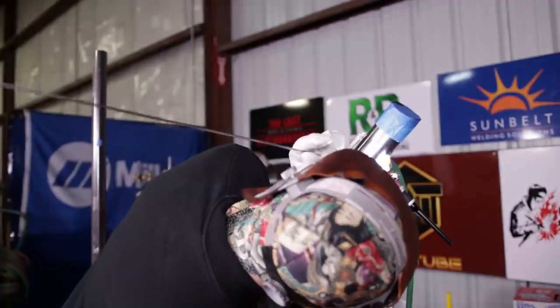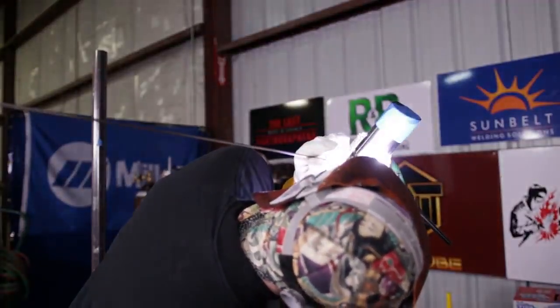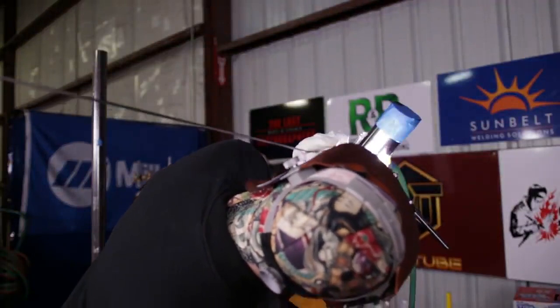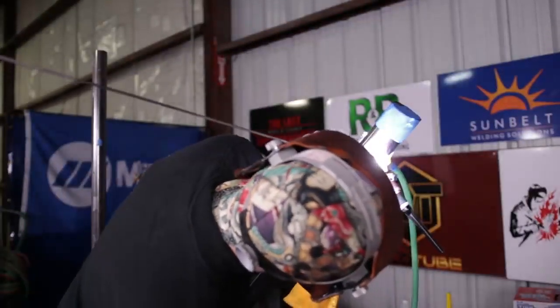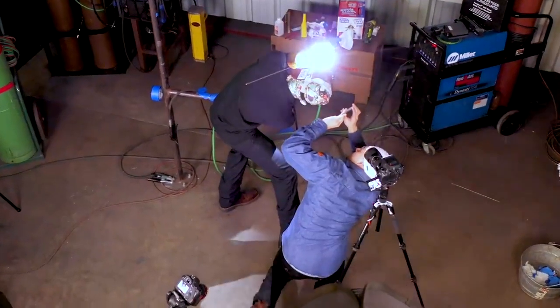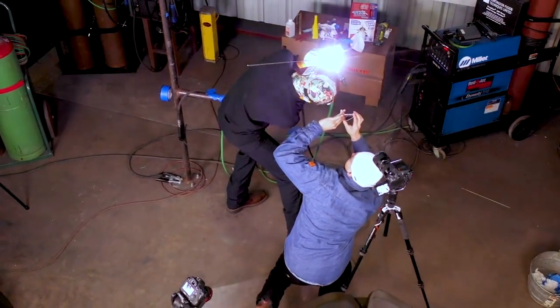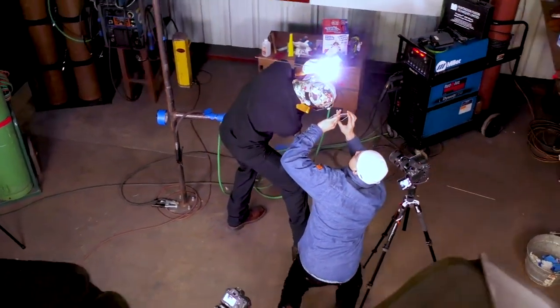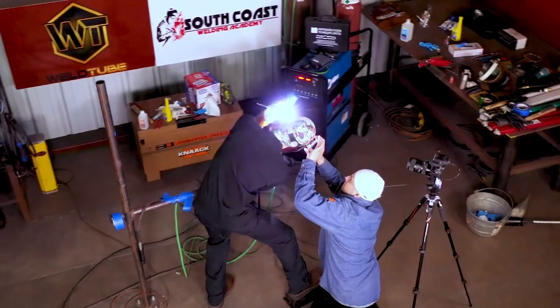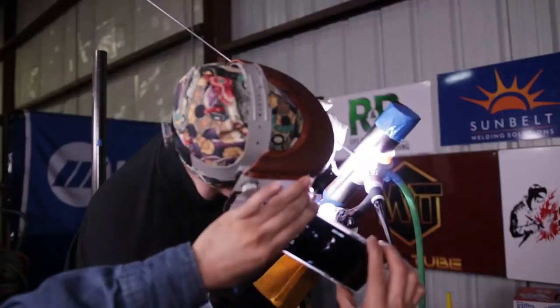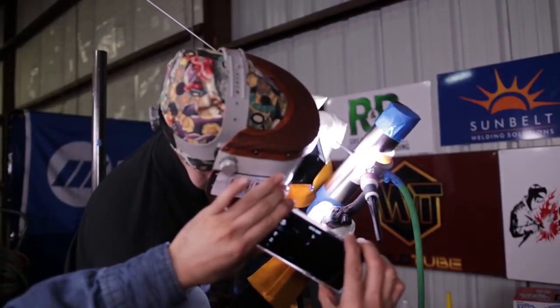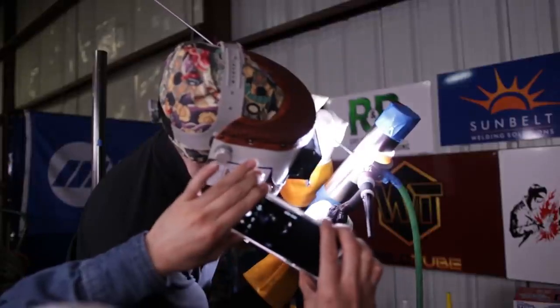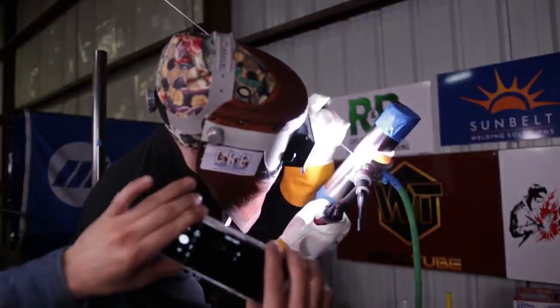Also, there's an accumulation over distance. Say if I weld 8 ripples on a hot pass with a 5356 filler metal, I can get away with, say, 8 ripples. That'd be about 150, 200 Fahrenheit, depending on how much energy I expel into the material. Each individual ripple you protect for 8 seconds. Overall, it'll come out as silver over the whole entire stretch of maybe about 2.5 inches.